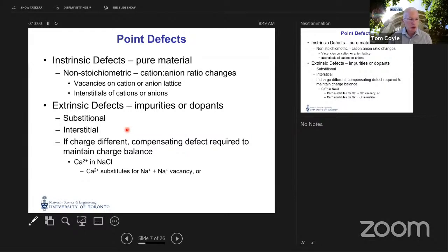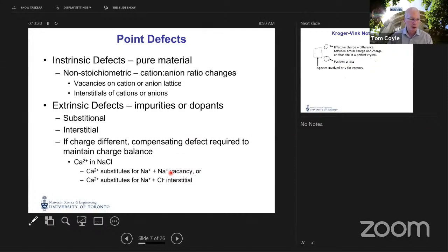And in order to do that while maintaining charge balance, the calcium would substitute for the sodium. That gives us an extra positive charge, and therefore we would create a vacant sodium position with a missing positive charge to maintain a balance of charge with the anions.